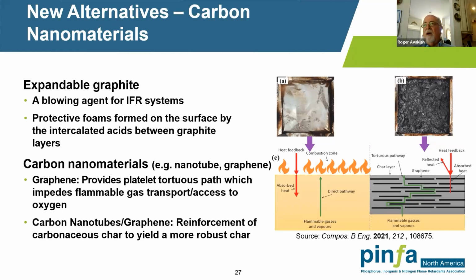And the carbon itself, the graphite that's left, is fairly non-combustible, and you do get this very large intumescent type of structure that is a very good thermal barrier. And since it is a platelet-like material, it does have this barrier to gases, either oxygen coming in or flammable gases going out. This is something that's been used for quite some time, and it's being looked at again. One of the negatives is obviously it works well if your system is going to be black, or you can tolerate a dark color. It's used a lot, for instance, for protecting polyurethanes and seating and things like that as a coating. So it's been around for a while.